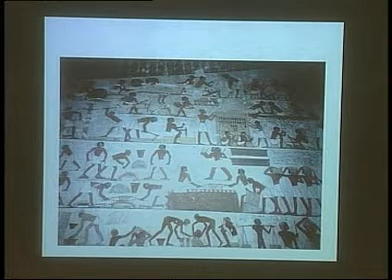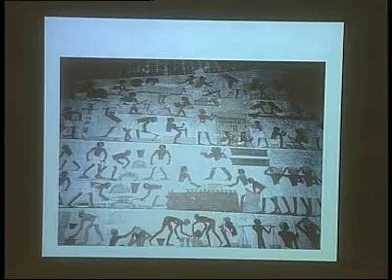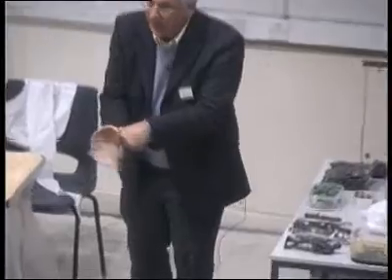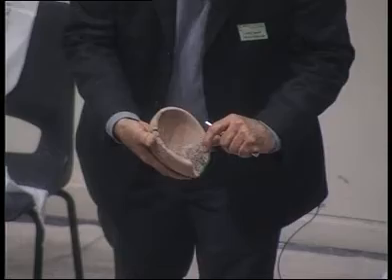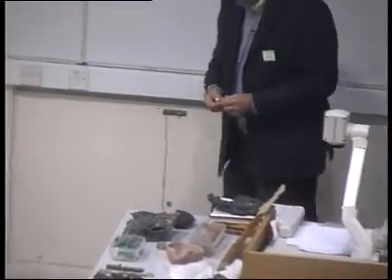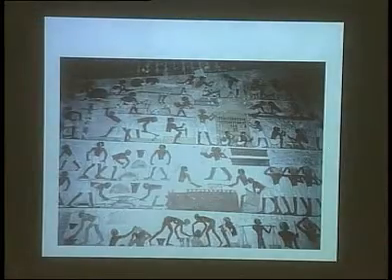And in our teaching collection, we have a reconstructed late Bronze Age crucible like this. How do we know what they were doing? Well, we'll go through and analyze specks of corroded metal inside. We'll look at the glaze on the inside, the color of the red, the color of the slag on the side, and we can assess the chemistry and what's happening from there. From the composition, we can also tell what the melting temperature is. Okay? That's the first point here.